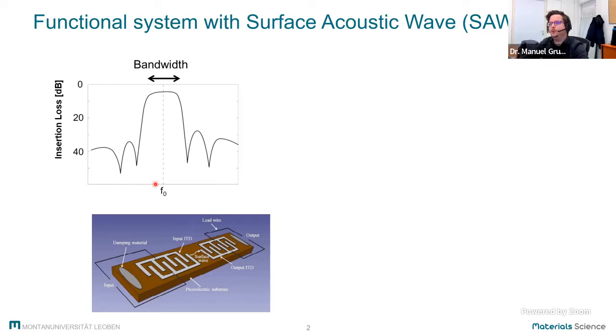One problem is that this center frequency can be temperature dependent. So if the temperature increases, for example, on a warm summer day, the dimensions between the fingers will increase. The Young's modulus of the substrate is also temperature dependent, and so the filtered frequency can change. And to handle this, there are certain single crystalline piezoelectric substrates with good properties, and certain cuts can overcome this issue with the temperature dependence.